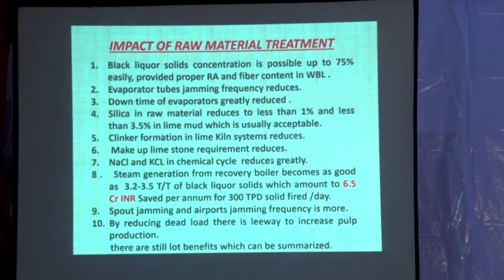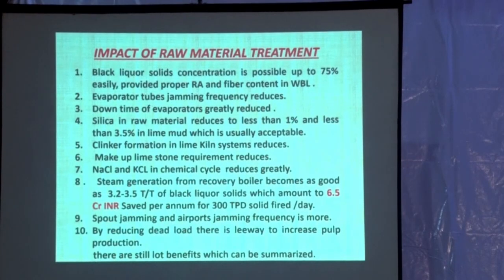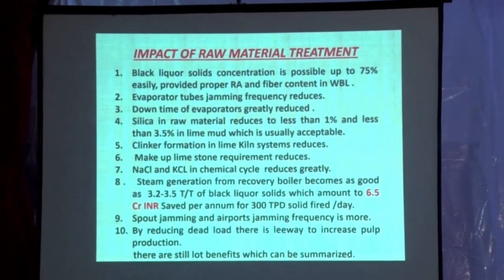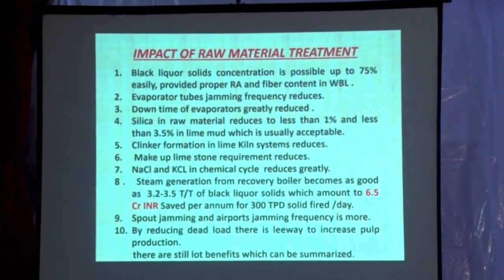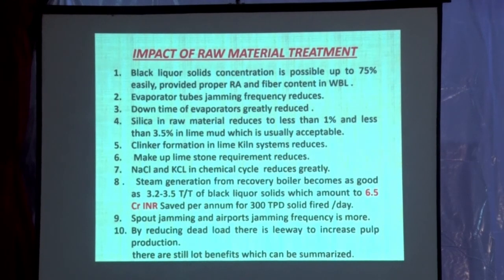Makeup limestone requirement will also be reduced. Why? Because as Dixit said, if we have 4 to 5% silica and we want to maintain 1% silica in the raw material mix, how much material we have to dispose of to maintain the silica? Approximately 98% of the lime mud you have to purge out. If there is 5% silica, I am talking about, and we have to bring it down to 1% in the raw material mix. Steam generation from the recovery boiler will become as good as 3.2-3.5 T/T of black liquor solids,